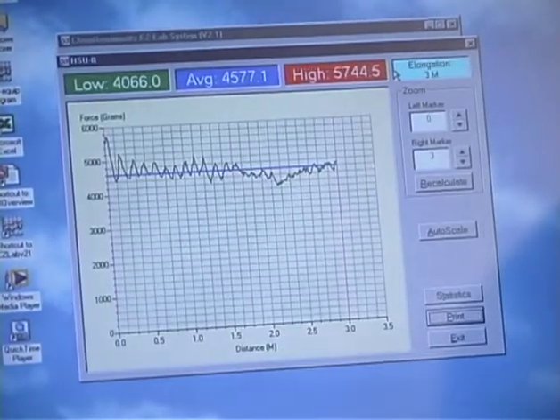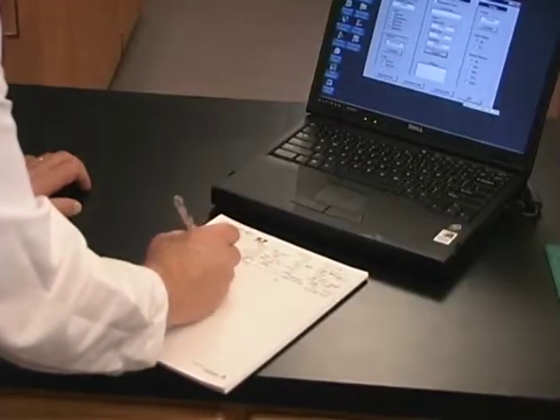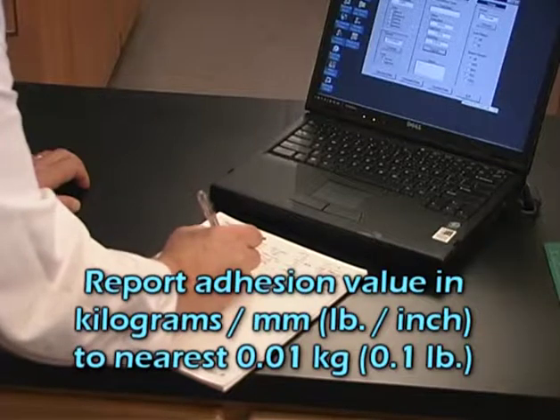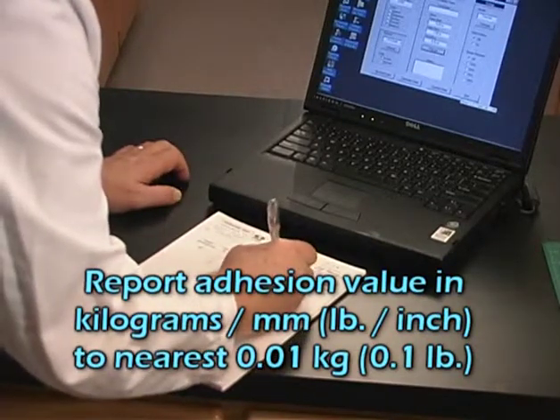Average the unwind force from the three areas tested and report the unwind adhesion value in kilograms per millimeter of width to the nearest .01 kilograms or other suitable unit.